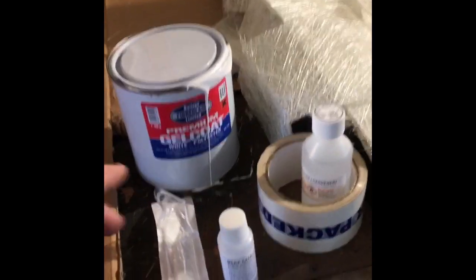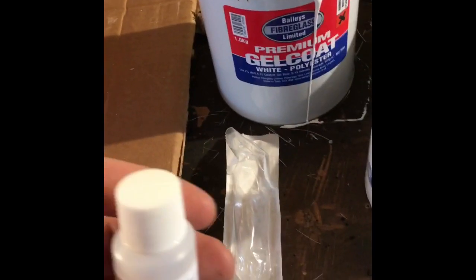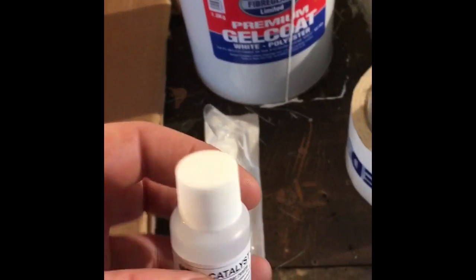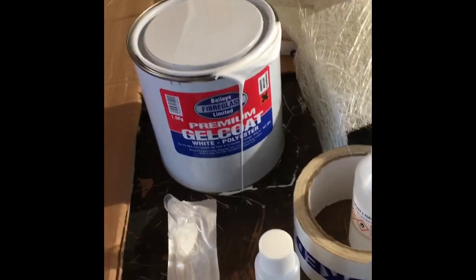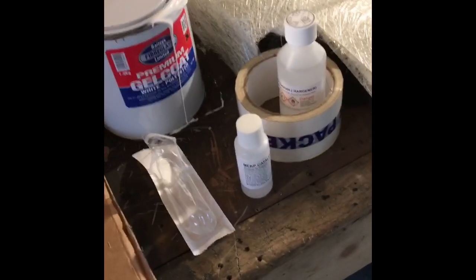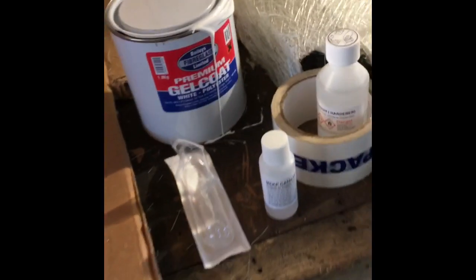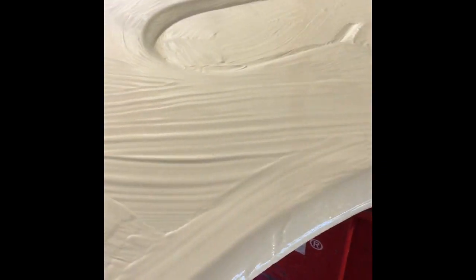But yeah, so the gel coat is a 2-part system. So it's got MEKP catalyst hardener with it, which by the way burns your skin. So for fuck's sake, don't get it on your skin like I did, because it does hurt. And that's 2% ratio. So to cover this door card, I've mixed 250 grams by weight to 5 ml by volume of catalyst, which I think or hope is 2%. Well, it should be anyway. But it goes off quite quick. You've got an 8 to 13 minute gel time, it says on the tin, but this is going off pretty rapid. So what you do, you paint that all over your mould, and that'll give you a nice glossy effect.